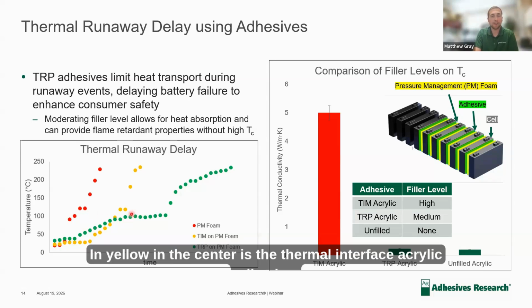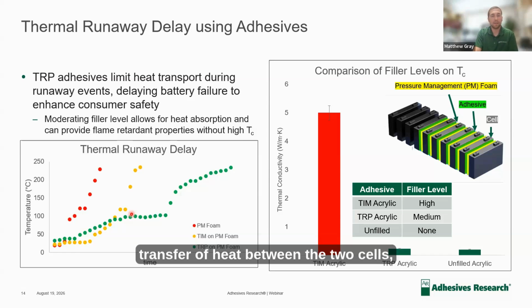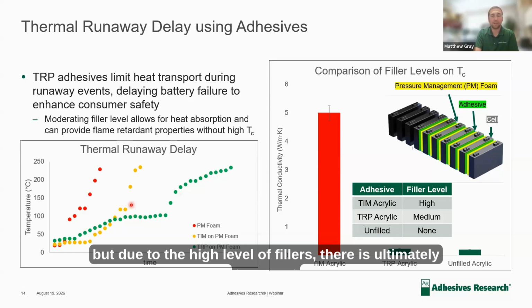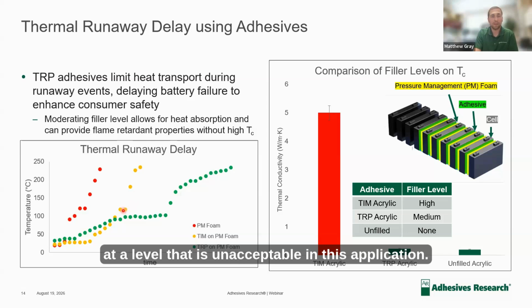In yellow in the center is the thermal interface acrylic adhesive. This material does have fillers which help prevent the transfer of heat between the two cells, but due to the high level of fillers, there is ultimately transport at a level that is unacceptable in this application.